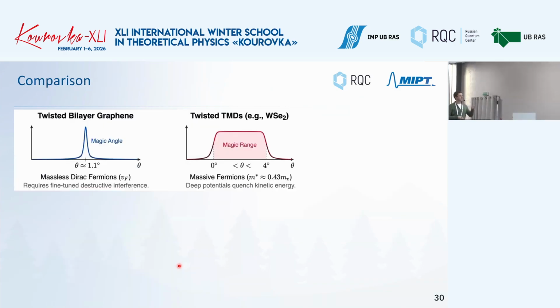energy potential are. And here's the comparison between the twisted bilayer graphene case and twisted TMDCs. I mentioned that there are massless Dirac fermions in bilayer graphene, and it requires very fine-tuned destructive interference, which happens around this 1.1 degree angle of rotation. It's very difficult to obtain. In the case of twisted TMDCs, the reason for this deep potential is the massive fermions, and the deep potential also quenches the kinetic energies, but this so-called magic range is much larger in degrees. So it's easier to make in the lab and easier to find out